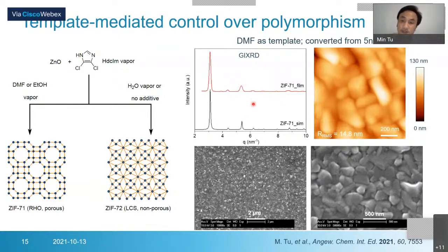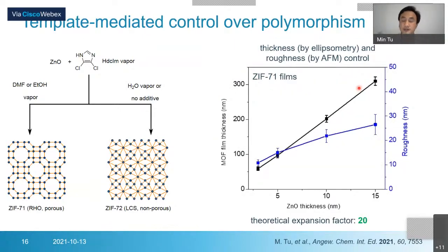When we use DMF as a template, we convert 5 nanometer zinc oxide. From the grazing incidence XRD we can see that we can get a ZIF71 film, and the film is quite smooth by AFM measurement and the SEM measurement. Then we can also control the thickness. The thickness is measured by ellipsometry and the roughness by AFM.